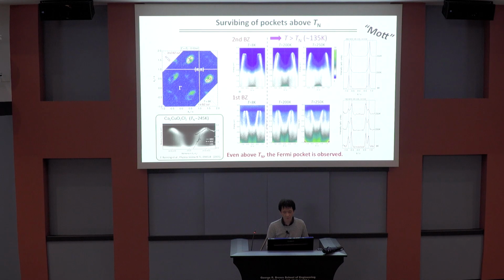Where you keep observing this pocket even around 135 Kelvin, above Tn. So our result for the multi-layer system is the Mott state, not the Slater case. In the Slater state, this pocket should disappear above Tn. So our pocket is really due to the Mott state.